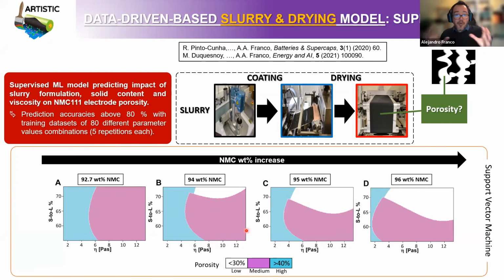Once again, this type of graph, I think, is very useful, in particular for technicians and engineers working in pilot lines, prototyping lines of batteries, because very quickly, thanks to this kind of phase diagrams, they can decide which slurry viscosity they need to have. This is once again connected to the coating speed and the comma gap that you have in a coater, and which solid content and which formulation you need to have in the slurry in order to get electrodes with the desired porosity, right?